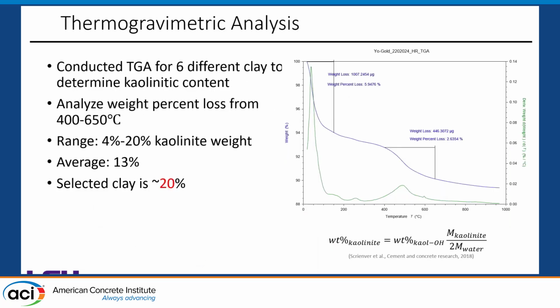Now, I know I've been talking a good bit about the kaolinite present in the clay, and the way that we determined it is through using TGA, or thermogravimetric analysis. We tried these on all 6 of the clay samples, and the process involves analyzing the weight loss that occurs from 400 to 650 degrees Celsius.